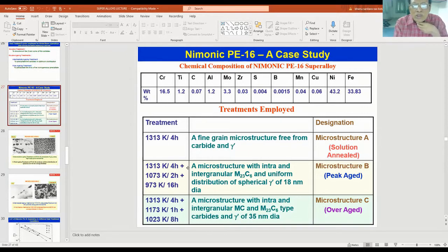I give a double aging treatment after solution treatment here for microstructure B to form gamma prime in the peak aged condition. Earlier graph you have seen that there's a critical size of 18 nanometers for this. By aging at 800 degrees centigrade, first I precipitated M23C6 carbides, and later at 700 degrees centigrade for 16 hours, I precipitated spherical gamma prime.